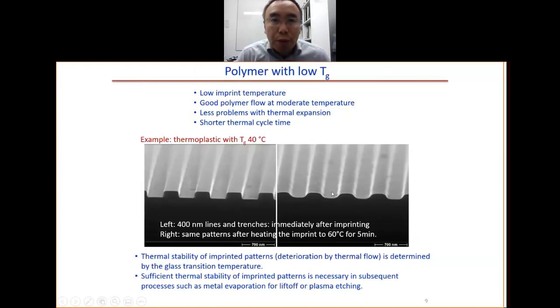So we know that when we have the lower glass transition temperature, we can do the imprint at a lower temperature, and also we get good polymer flow at the moderate temperature, a smaller problem for the thermal expansion, and the shorter thermal cycle time. They are all good properties. But the problem is when the Tg is too low, for example, in this case, it's only 40 degrees. This is the pattern after imprint. Then after 60 degrees for 5 minutes, you see the polymer reflow, so the pattern gets degraded.